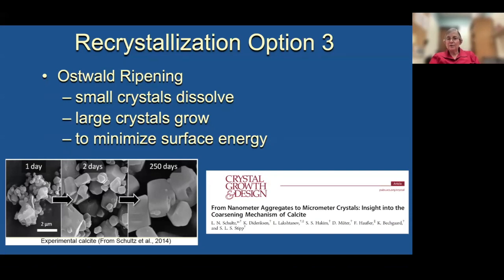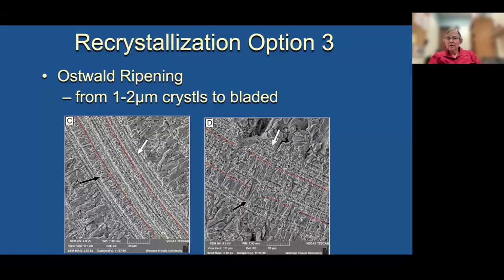So small crystals have a greater surface area, and therefore they're less stable than big crystals. And so a crystal starts to dissolve, big crystal steals the calcium carbonate, little crystal dissolves more. So it's a solution cannibalization reaction until you end up with crystals that are stable. This is what I think is happening in our stuff here, is that we're starting with 1 to 2 micron crystals, and they are inherently unstable, even if they are calcite, and that what you get out of it is the bladed calcite. If this went over more time, because these are very young, that bladed calcite likely goes to even coarser. But I don't know at what point recrystallization would stop. I don't know where you get a big enough calcite crystal that it's stable. These fabrics are present in pearls that are much older.